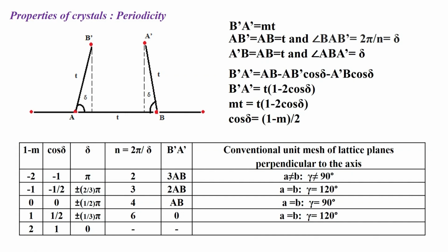And the same logic can be extended to 3 dimensions, and therefore, the rotation axes are 1, 2, 3, 4 and 6 only, and no other rotation axis is possible. This can be easily seen in a physical situation. Suppose you are given 5-fold type tiles and you are asked to fill the entire floor of this room, you will see that it is not possible to do a close packing. As we have been discussing earlier, all our diagrams in Escher's pictures are close packed.